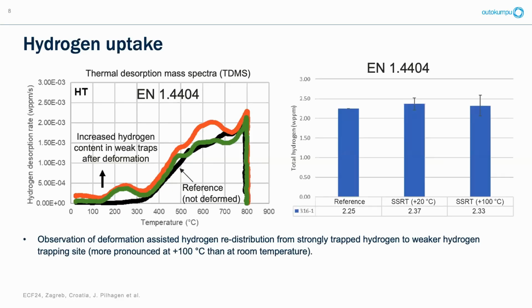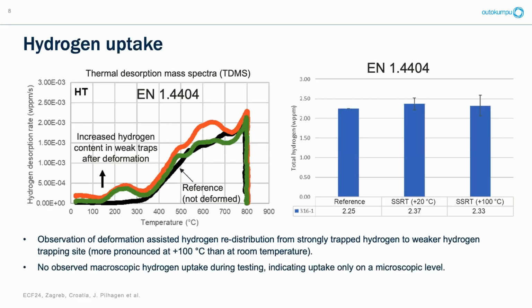And the reason why we believe it's actually from the deformation and not picked up during the testing is that you can integrate these curves and see the total hydrogen content, and it is in principle the same. We also verified it by melt extraction, and I think we also did a test in argon gas and saw the same thing. So one other conclusion is that there is no observed macroscopic hydrogen uptake, but we do have embrittlement in some cases, so that indicates that the uptake is only on a microscopic level.